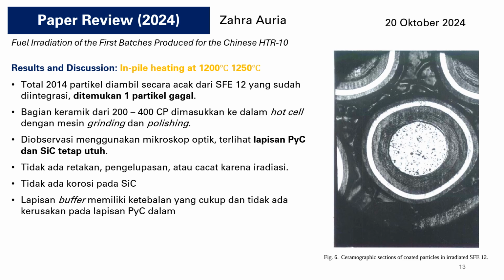From the ceramic parts, 200 to 400 coated particles were inserted into the hot cell with the grinding and polishing machine, and they would be observed with optical microscopy. In this figure we can see that the silicon carbide and pyrolytic carbon layers are still intact. There is no fracture or defect from the irradiation, and also no corrosion on the silicon carbide. The buffer layer had enough thickness, and there is no damage to the inner pyrolytic carbon layer.